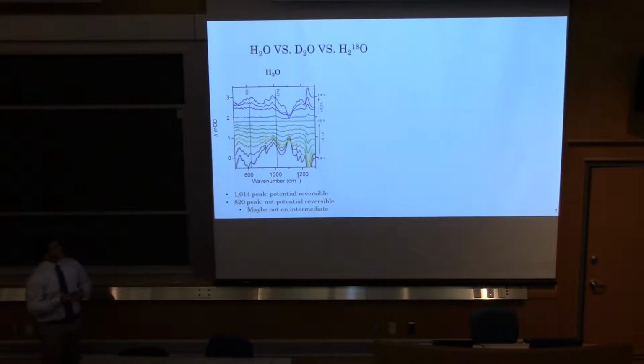It's very hard to tell because we have this interference from phosphate from our electrolyte here. But we believe this to be one of our intermediate species, and you can see at the higher potentials it's present, but as we decrease the potential, it decreases, and it's also reversible, as you can see it back up here. We also notice a second intermediate possibly down here. However, there's no presence as we increase the potential again,